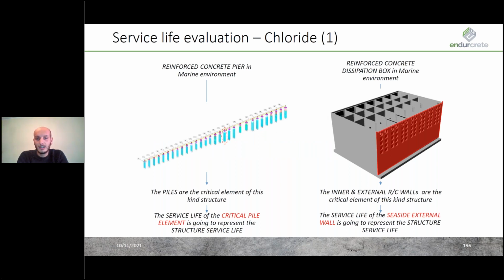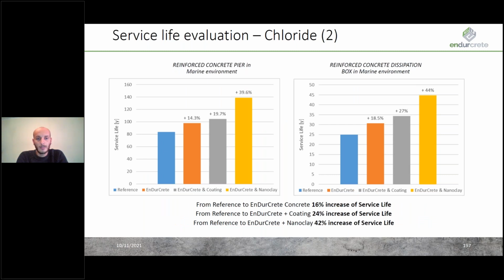In the first case, we analyzed the concrete diffusion, and in order to do that, we analyzed 2 different kinds of structure. The first one is a reinforced concrete pier, and the second one a reinforced concrete dissipation box, both in a marine environment. Basically, here we analyze the critical pile element for the first structure and the critical external wall for the second one in order to evaluate the service life of these structures. So in this case, we obtain the evaluation of the service life.